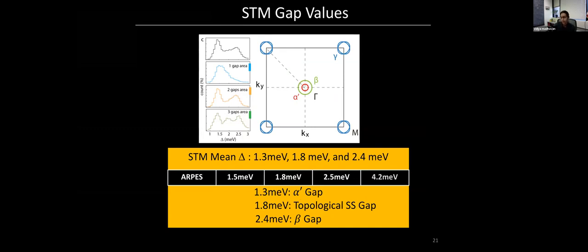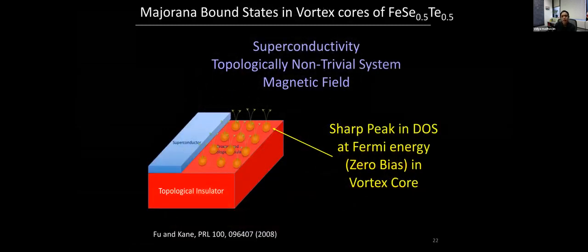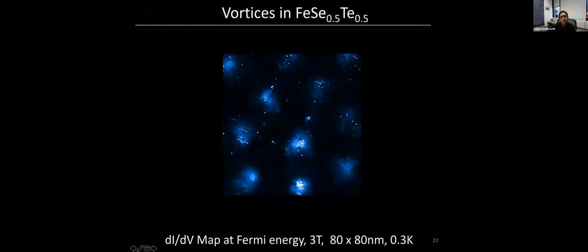I'm showing you all this basically to establish that these samples are very consistent across ARPES and STM. Okay, so now we can turn on a magnetic field and look for these Majorana bound states. And so here's a dI/dV map showing vortices. You can almost see a hexagonal arrangement of the vortices here.